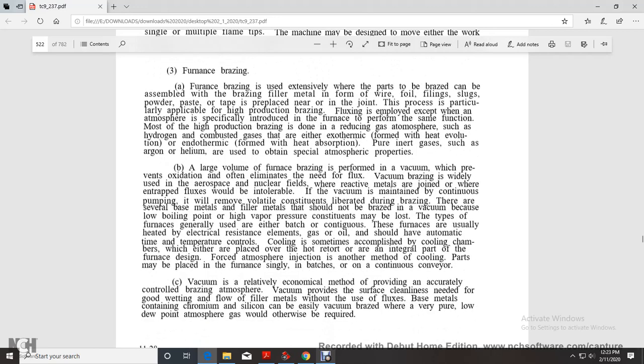Furnace brazing is used extensively where the parts to be brazed can be assembled with the brazing filler metal in the form of wire, foil, filings, slugs, powder, paste, or tape, and placed near the joint. The process, particularly for high production brazing, is employed with flux except where an atmosphere is specifically introduced into the furnace to perform the same function. Most high production brazing is done with reducing gas atmospheres such as hydrogen, combustible gas, exothermic form with heat evolution, endothermic form with heat absorption, and pure inert gases such as argon and helium, which are used to obtain special atmospheric properties.